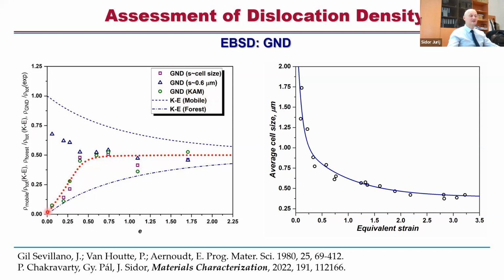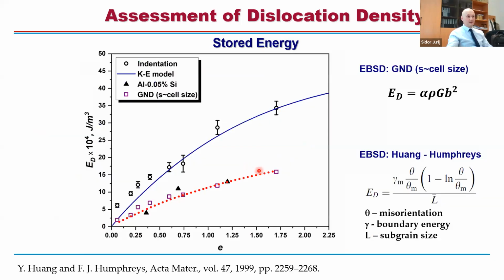And in fact, it's physically sound that the amount of GND tends to increase with the straining level. And what was very interesting to observe is that this line tends to saturate at almost 0.5, 0.48, something like that, right? So almost half of the dislocations which are generated are GNDs. The rest are trapped. So 50% will be trapped, and we call them statistically stored dislocations. So here you also have from the model mobile dislocations and forest dislocations. They are, I would call, upper and lower bounds.